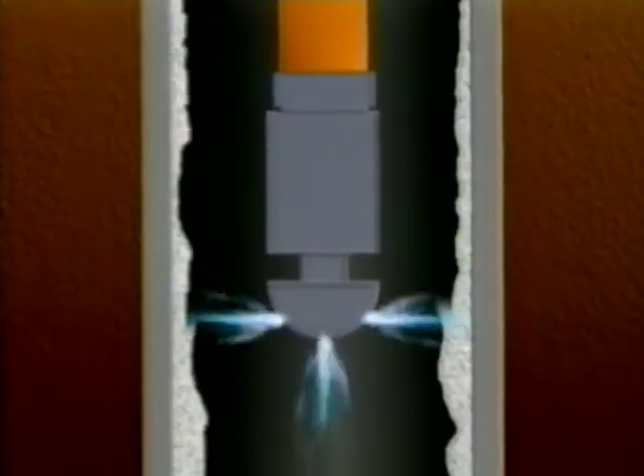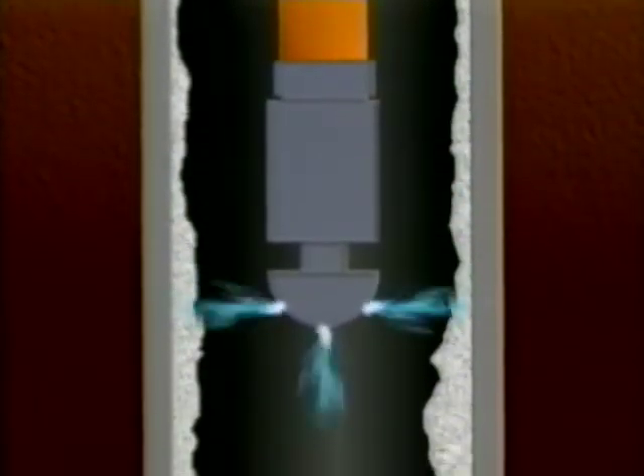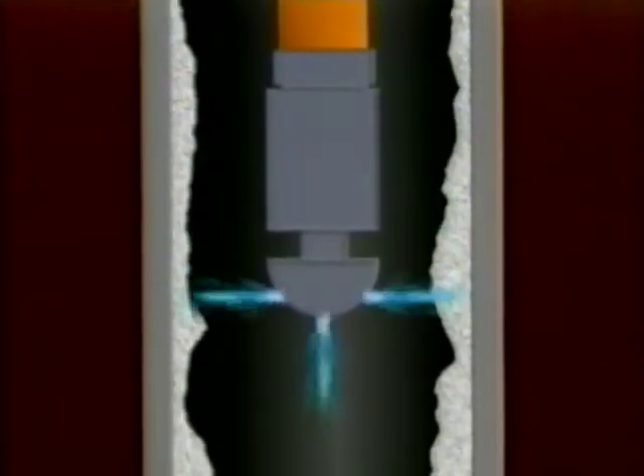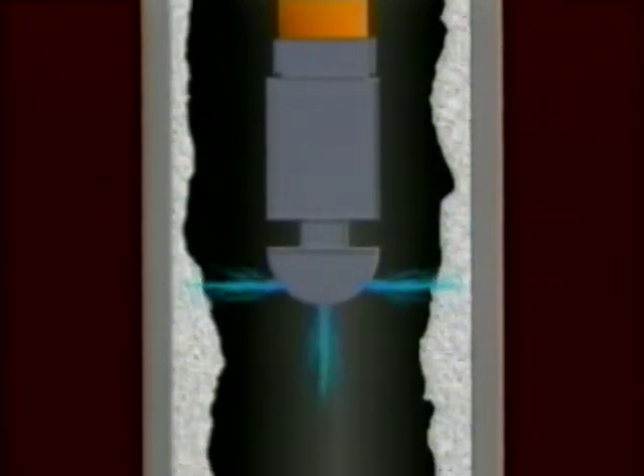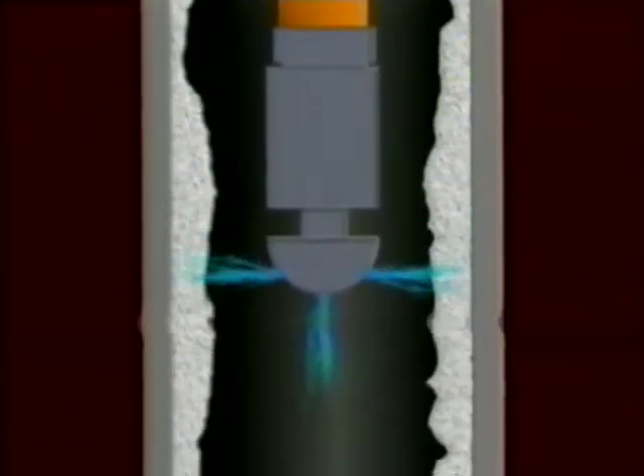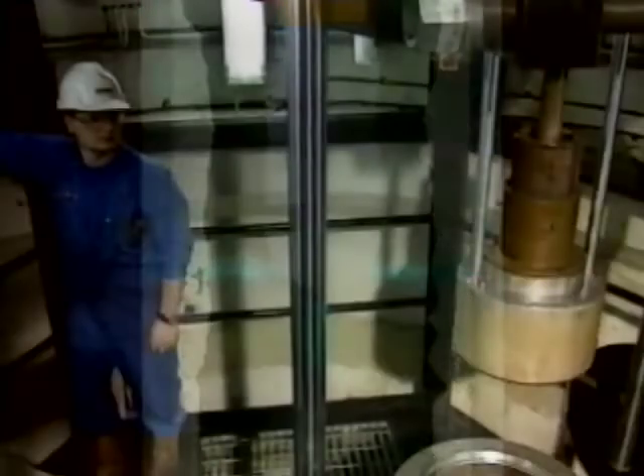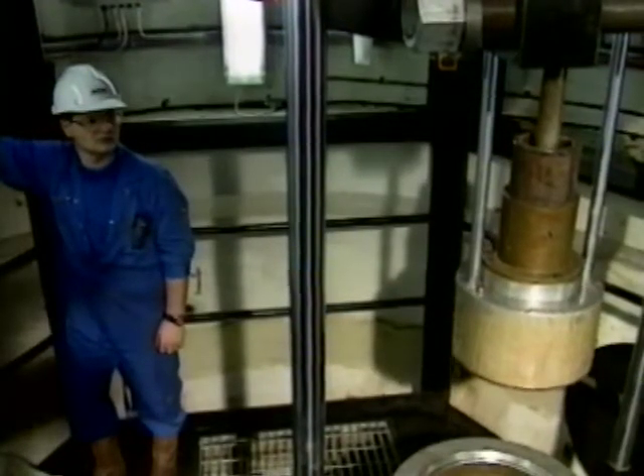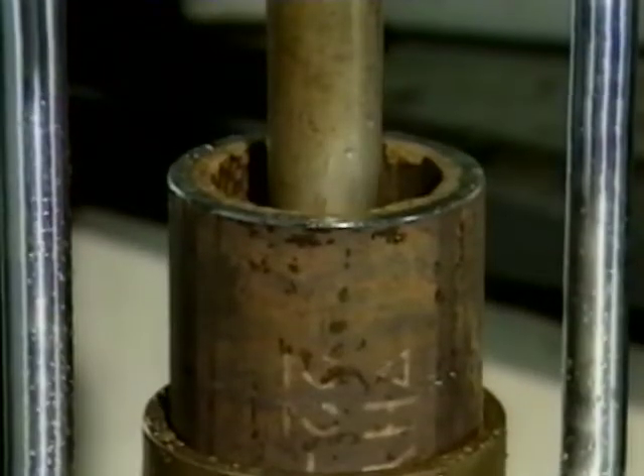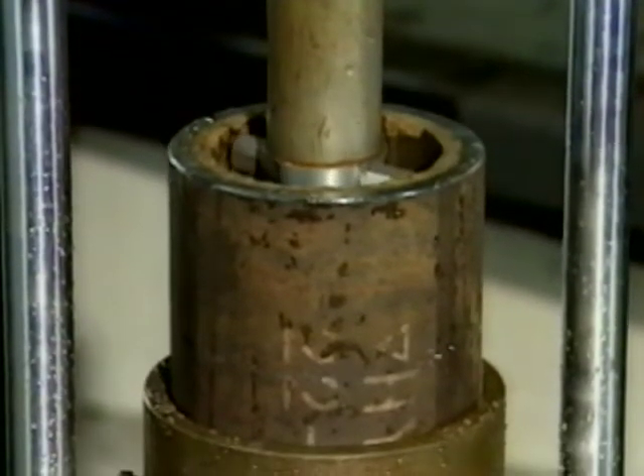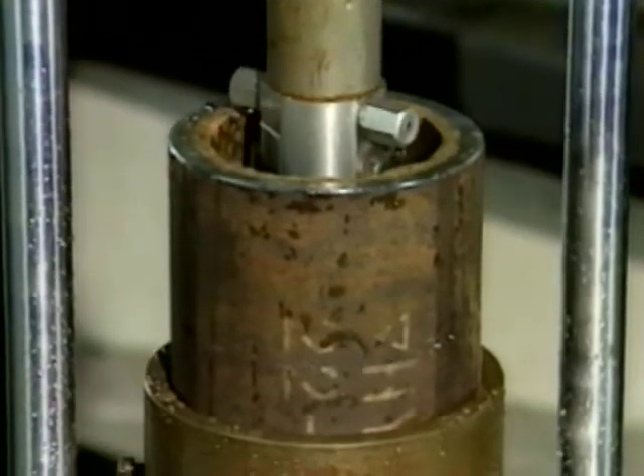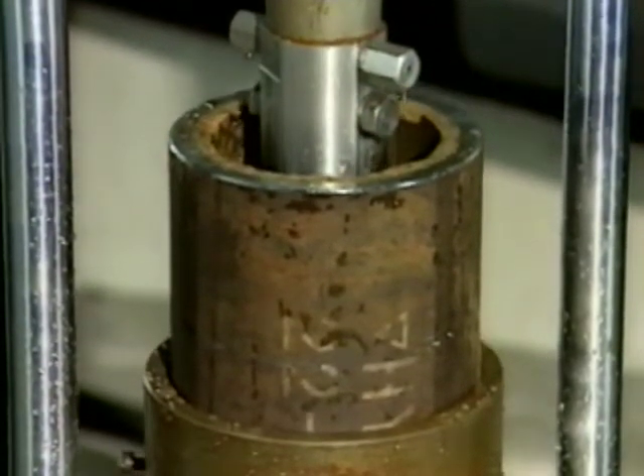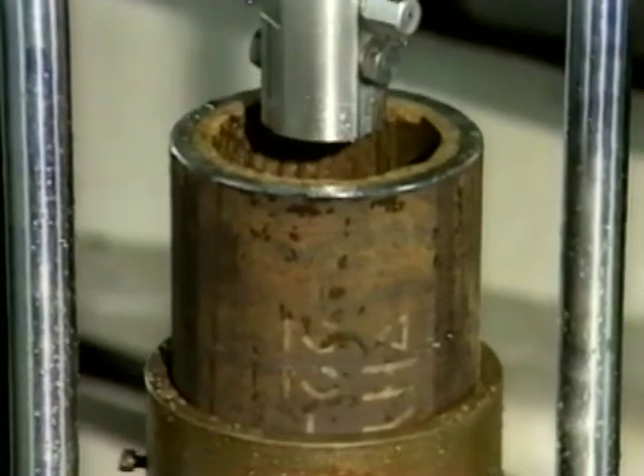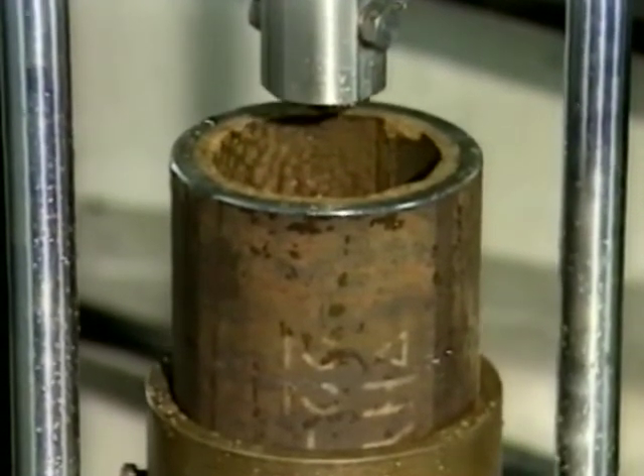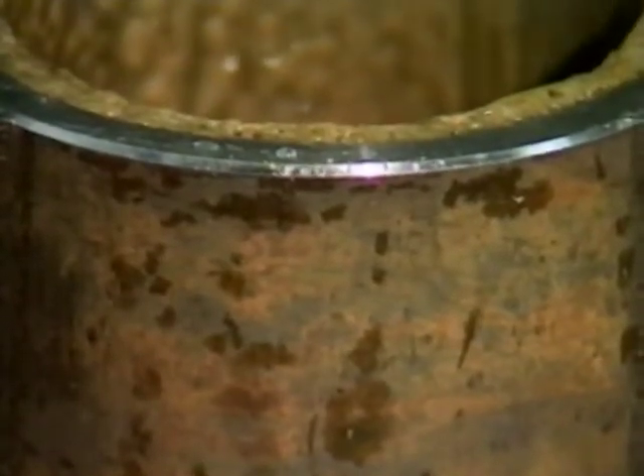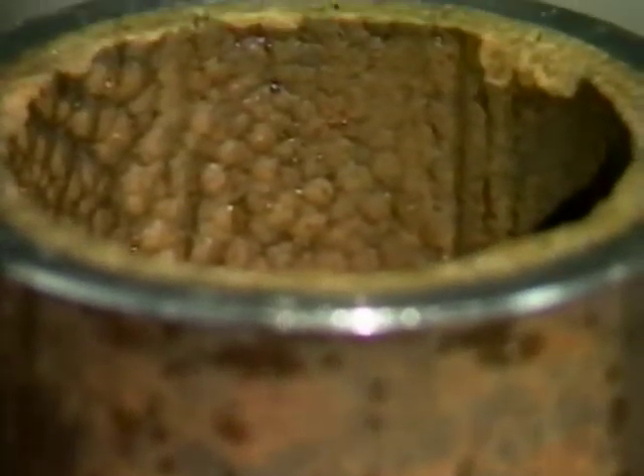At downhole pressures, however, the formation of these bubbles, as well as the erosive cavitation effects, are suppressed. Typically, a jet is 4 times more erosive close to the surface than in downhole conditions. In other words, a jetting scale removal system may work effectively in a yard test or in a shallow well, but under realistic downhole conditions, the performance may be impaired considerably. Tests of scaled tubing recovered from a producing well show that a pure water jet without the use of dissolvers is almost totally ineffective.